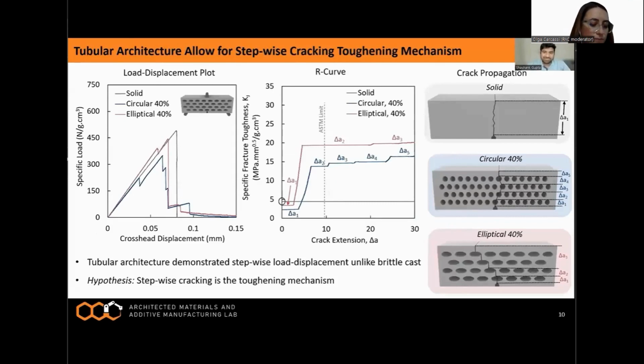So, what did we find? Let me show the highlights of some of the results for some of these designs. The load displacement response of notched specimens demonstrates that the architected tubular material, represented by blue color and the red color, shows a unique non-brittle fracture behavior compared to the brittle solid counterpart shown by the gray line. The architected tubular design demonstrates multiple hardening and softening behavior, which is evident from the multiple crack initiations.